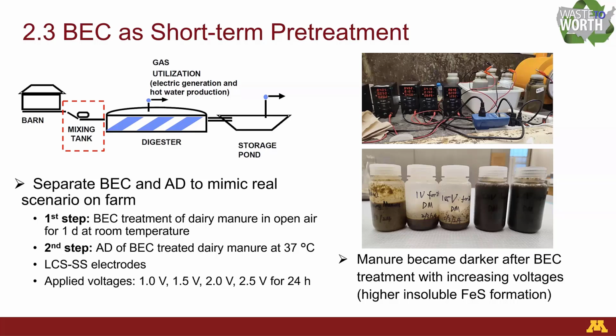So first stage is the BEC treatment or pre-treatment of the manure in open air at room temperature for 24 hours. Second, then the treated manure will be subject to anaerobic digestion under mesophilic conditions. According to the selection of electrodes, we choose low carbon steel and stainless steel as the cathode. The applied voltage ranged from 1 to 2.5 volts for 24 hours.